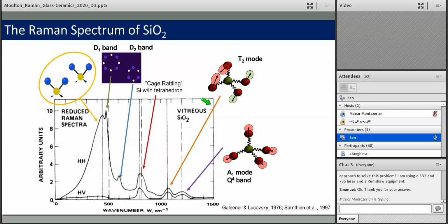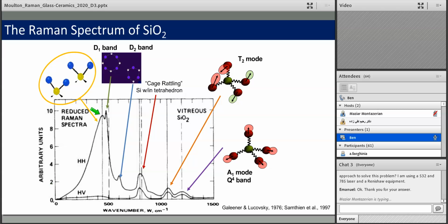So, starting with the most studied glass by Raman spectroscopy, here is a spectrum of silica. And you see that at low frequencies, below 500 or 600 wave numbers here, you get this really big broad feature. This is described in most of the literature as the main band. We mentioned earlier that at low frequencies are the bending and rocking modes. And so most people assign this to these, but we really have no way to tell because it's a very broad, featureless envelope that anything could be under there.